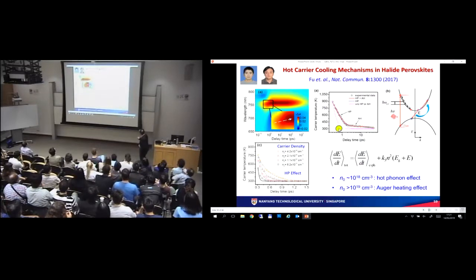Now, the main finding is that for pump fluences up to about 10^18 cm^-3, the hot phonon effect dominates. More than 10^19, you have an Auger heating effect that comes into play, and that is the mechanism that drives the hot carrier cooling in the halide perovskites.